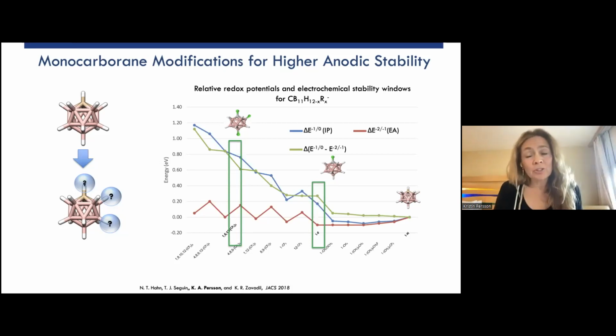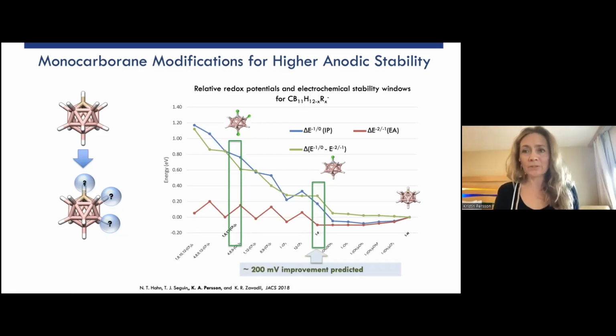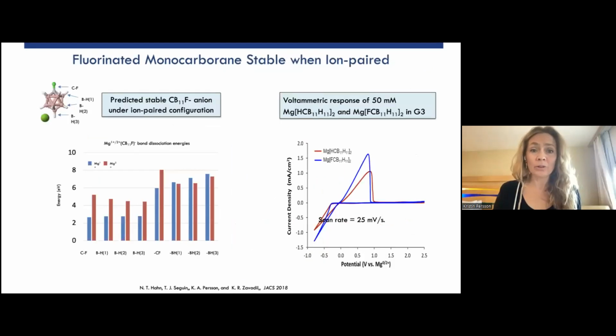And no big surprise, we tried a lot of different functional groups, but of course, chlorination is known to improve the electrochemical stability. We really like the trifluorination, but our experimental counterparts, again, Kevin Zavadil and Nathan Hahn, were a bit skeptical whether they could make that one. So they focused on the single fluorinated monocarborane, which is shown here in the middle, and would gain us about 200 millivolts, pretty modest, but still we thought it was a good proof of concept. If we could make this one, it should have higher anodic stability, and hopefully we were also able to calculate that it would still retain its stability against the magnesium 2 plus, or the plating conditions. So this was a promising anion, we believed, with a slight modification from the Toyota model.